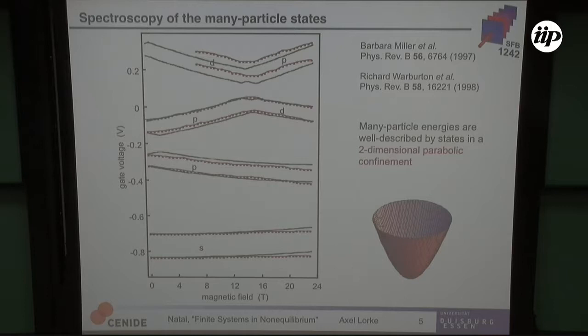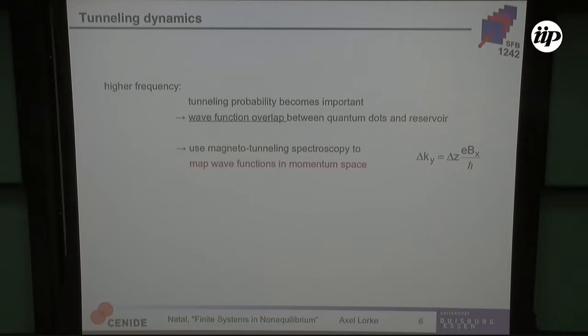Okay, but we want to talk a little bit about dynamics. So let me first talk about tunneling dynamics. So what happens when you increase the frequency with which you probe this density of states, with which you probe the tunneling of the back contact into the quantum dots? At some point your frequency will be so fast, it will be faster than the average tunneling time into the dot and back. And then this amplitude will no longer be just the density of states, it will also be affected by the tunneling probability. And the tunneling probability, again, is given by the wave function overlap between the quantum dots and the reservoir.